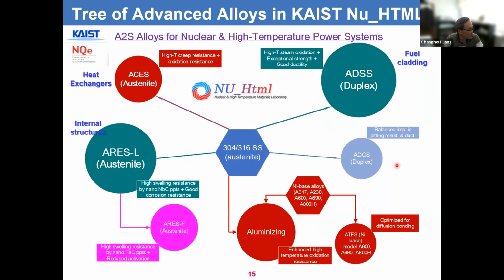To fulfill those requirements, in our lab and our research group, we have developed several different advanced metallic materials based on stainless steel. We have developed the ADSS, a duplex stainless steel, aiming for application as advanced fuel cladding. And we have the so-called ARES alloys. They have austenitic structures, but exceptionally high radiation resistance. And we also have other austenitic alloys whose compositions are optimized for good performance in high temperature heat exchangers. There are others, but in this talk, I'm going to talk mainly about these three alloy development statuses.